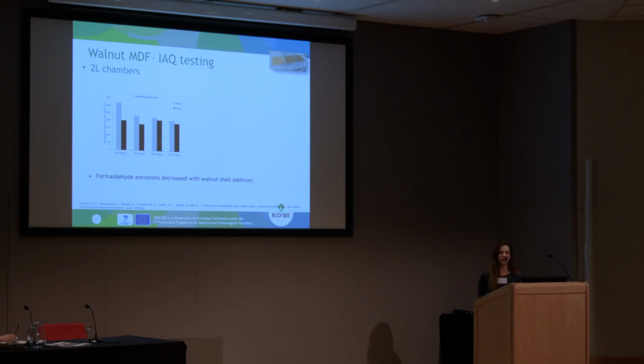So they added this walnut shell into the MDF resins, and then they studied the formaldehyde emissions from these materials, and they observed that by increasing the walnut shell, the formaldehyde emission decreased. So then we also followed that study, and we added walnut to the resin prepared for these MDF panels. These materials were prepared by Bangor University, one partner of our project.